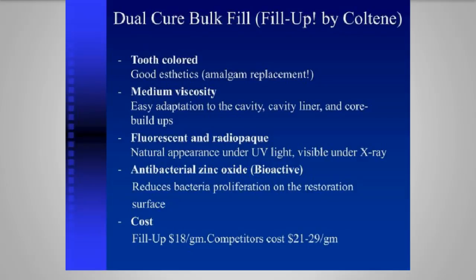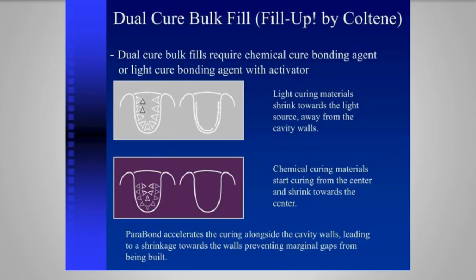We'll talk about the colors of this versus a traditional bulk fill that might be more translucent. But another one that I commend Coltene for is the bioactivity, because as you know, glass ionomers have the ionic exchange adhesion, calcium, the phosphate, and fluoride. This has zinc oxide, which is bioactive, which reduces the proliferation of bacteria on the restoration. So this is bioactive, gaining popularity, a term that we're all becoming much more comfortable with. Again, $18 a gram. Now, with the bulk fill dual cure, you use the ParaBond here.